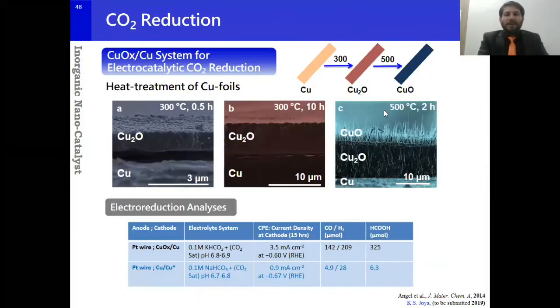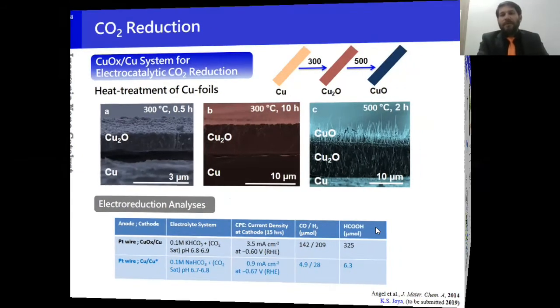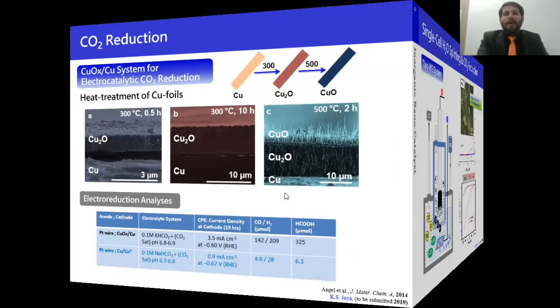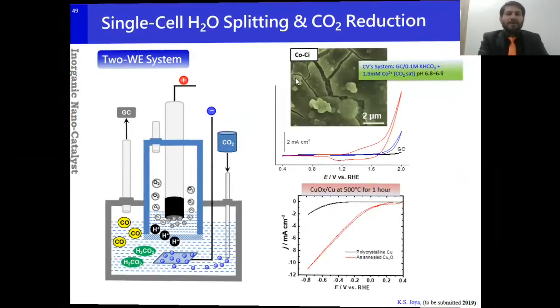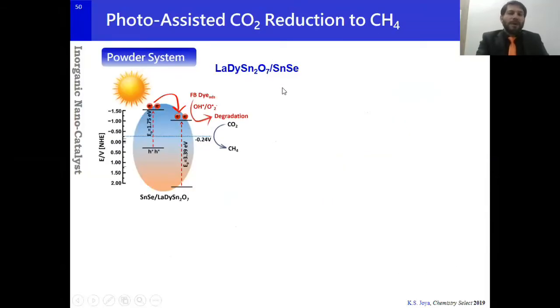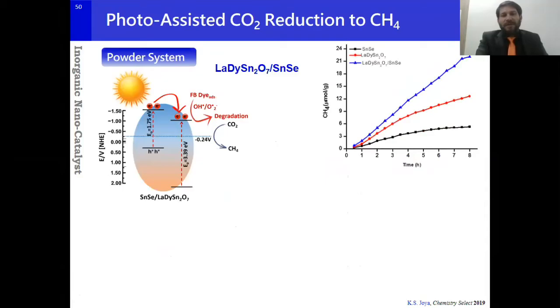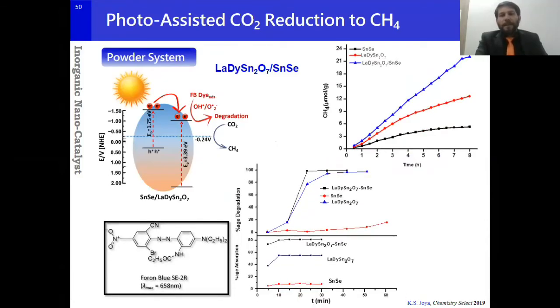In this case, you can see we developed these copper oxide nano hairs, and they perform, let's say, exceptionally well compared to simple copper oxide for reduction of carbon dioxide into syngas and also into formic acid. Okay, then of course this is our recent work coming from a collaboration. So we developed this composite material which is photosensitive, and it is able to convert CO2 directly into methane gas. Of course, we also performed the experiment for the degradation of this Foron Blue dye also.